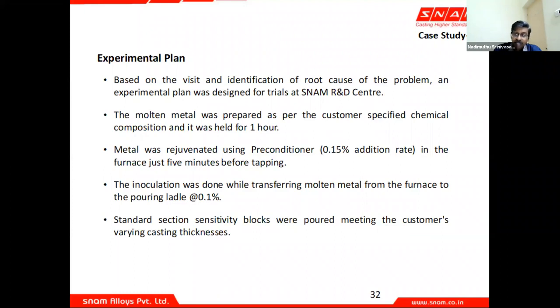And the molten metal was as per the chemical composition we took from them, and we held it for 1 hour. We rejuvenated the metal with a preconditioner, at an addition rate of 0.15% in the furnace, just 5 minutes before tapping. It was a barium calcium based preconditioner, 1 to 10 mm size. And inoculation was done while transferring the molten metal at 0.1% addition, which is what they practice.